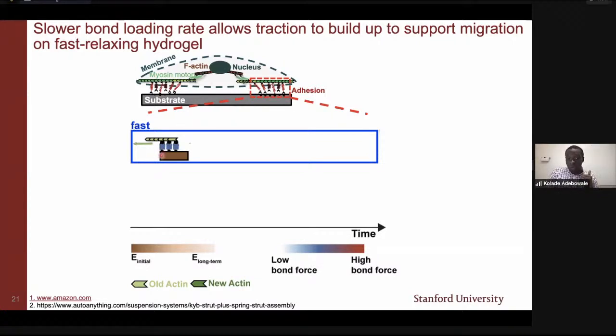And the substrate is color-coded specifically because these substrates are stress relaxing. So what that means is if they're pushed on, they have an initial Young's modulus. However, that initial Young's modulus can decrease as a function of time, and that will be represented by a lighter brown color in a second. The other thing that I'd like to highlight is that these springs are being pulled to the left in this schematic due to the retrograde flow of actin. And so those springs come under load, and the springs will be color-coded such that the darker colors indicate a low bond force, and the warmer colors will indicate a high bond force.